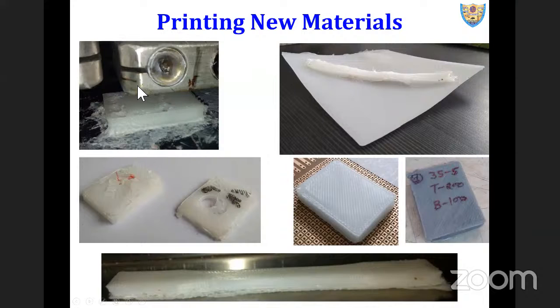When we started printing HDP, there were multiple defects here. Warpage was too high. This is the base plate, which also warped in addition to the sample. After half of the printing of the sample, at around 1.5 millimeters, the sample warped and while warping, it made the base plate also warp. All of us know, whichever material you are printing, you need to prepare a compatible material paste and put it on the glass bed of the 3D printer. So we had an HDP plate because we are printing HDP. And this is what we observed. So you need to tweak the parameters, as I mentioned: printing temperature, printing speed, chamber temperature, and bed temperature. We tweaked them, and then we were able to get such a good, nice sample, which is made up of high density polyethylene.